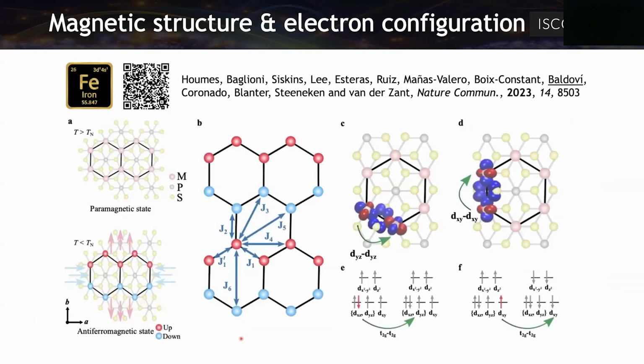Then we go to our orbital resolved model to test what are along these directions the main mechanisms. And we have two ferromagnetic mechanisms. One is in J1 along this direction, another one is in J2 along this direction. In this case, the material behaves ferromagnetic along this direction. So the system with this kind of compression along this direction is favoring the hopping of this electron from the dxz orbital here to this one that is empty, for this pair to this pair. And in the case of this direction, this expansion is making more difficult this hopping, because here we have antiferromagnetic interaction.